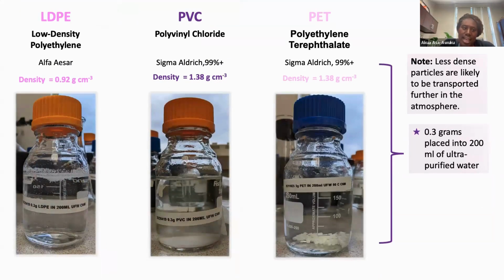So how we did the study is that we took about 0.3 grams of each of these plastics, and we placed them into 200 milliliters of ultra-purified water. And so we acquired these samples commercially. They're typically 99+% grade versions of these plastics. And what we did is that we just placed them in solution. And so if you look carefully, you can see that the pellets, LDPE, which is lighter than water, actually float on top of the solution, whereas PET, which has a density of 1.38 greater than water, drops to the bottom. And that's also true for PVC as well.